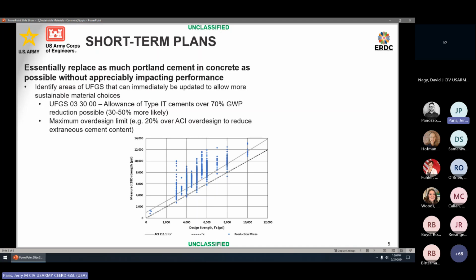So if we include an additional 20% over the over design as a theoretical maximum over design, what we find is that these mixes that are shown in red are considerably over designed. So for instance, the mixture is at 3,000 PSI. There's no need to have 8 to 10,000 PSI strength concrete when your design is 3,000. So you would be limiting it to about 5,000 maximum. And that requires the cement loading to reduce.